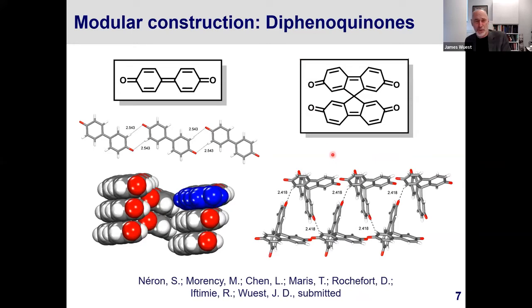So we've extended this considerably, and when I say extended, I mean it literally. We've moved from benzoquinones to these compounds that are called diphenoquinones. So here's a structure. These compounds have actually been known for a long time. This particular diphenoquinone was first reported by Willstetter well over 100 years ago. But the compounds have remained exotic, poorly understood, never examined crystallographically. Information about redox properties is scattered in the literature. The compounds are highly reactive. But when you know how to make them and to crystallize them, they can be characterized in a complete way.